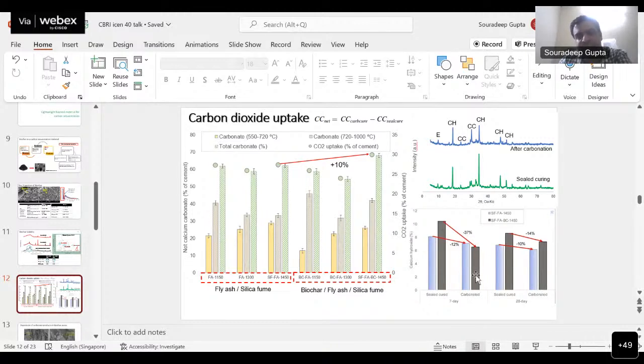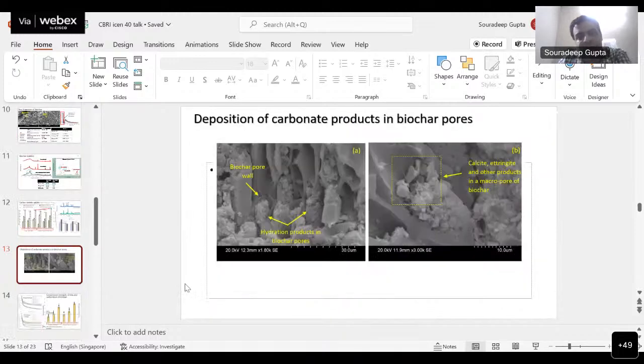We have also cross-validated the data with thermogravimetry: the decomposition, or reduction, of calcium hydroxide is higher in biochar mixed lightweight mortar compared to that without biochar, which means that more and more calcite is being contributed due to the action of biochar, and the contribution from the decomposition of binder will reduce. Why is this so? That's very interesting. It is because the pores of biochar act as nucleation sites for the precipitation of calcium hydroxide, which will turn into calcite and other carbonation products inside the pores of the biochar. And biochar is a filler, at least from wood waste. It doesn't have any pozzolanic action, and therefore the contribution of calcite also increases.